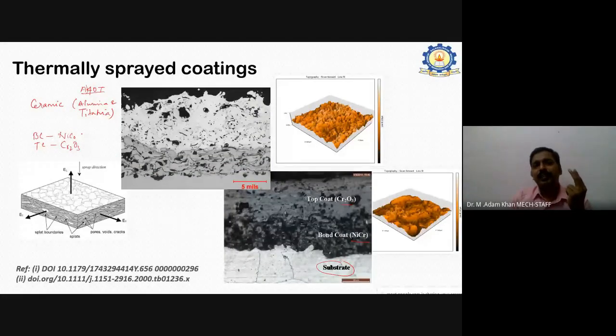You can see the differences between the ceramic first coating and the second coating. The main difference is that there is no ceramic in mine, because it is a metallic oxide. This is not a ceramic. This is also a pure metallic. So there is no chance of forming alumina even when it is exposed to higher temperature. I have not taken yttria. I have not recommended zirconia. I have not recommended any sort of ceramic forming oxides in my coating.